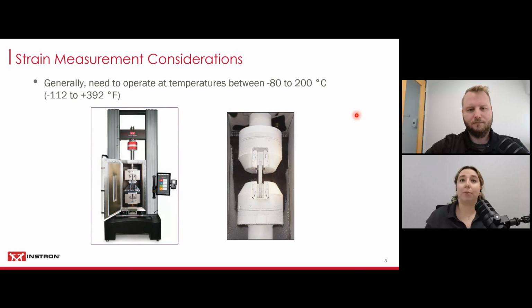Generally, we need to operate at temperatures from -80 to 200 degrees Celsius. Chamber units can typically provide these low temperature or high temperature testing environments. The picture on the left is actually showing a compression after impact fixture that's been piggybacked between some wedge grips inside of a chamber.